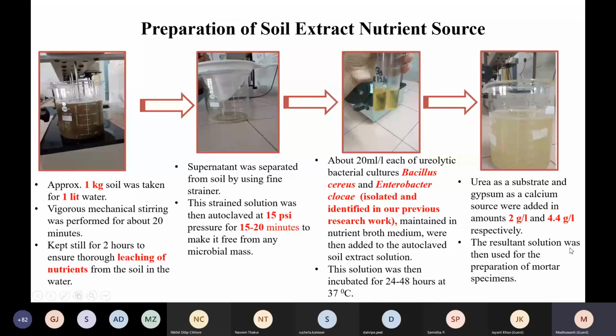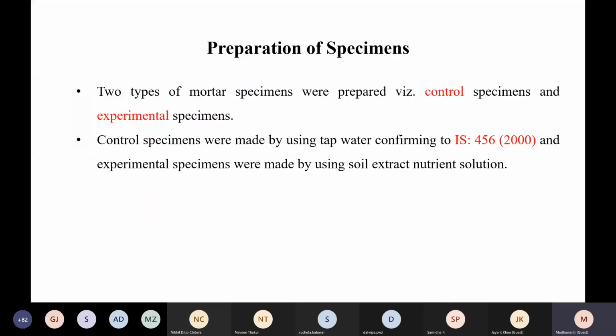So this resultant solution or suspension was then used for preparation of mortar specimens. As you can see, we have not used soil; we have decanted and taken the supernatant. Now, for preparation of specimens, two types of mortar specimens were prepared, control and experimental. Control specimens were made using tap water, and experimental specimens were made using soil extract nutrient solution. As I told you earlier, we entirely replaced the water when we cast the experimental mortar specimens by the soil extract nutrient solution which we have prepared here.